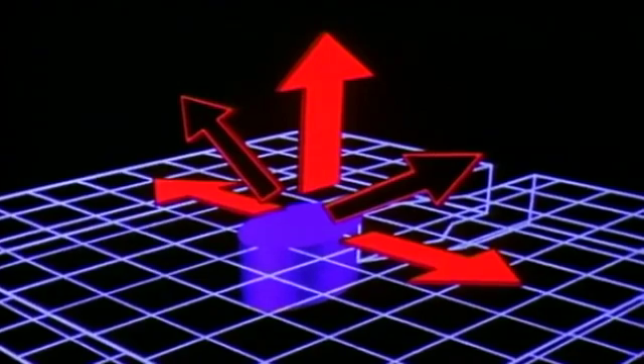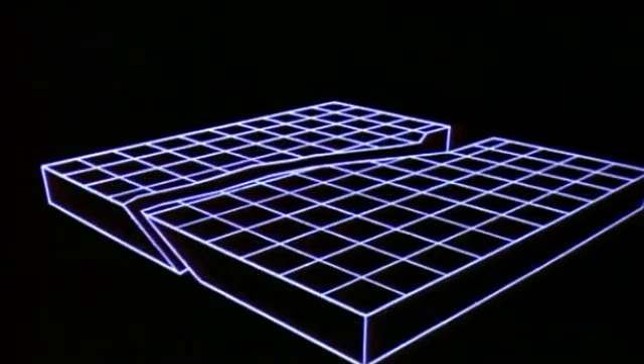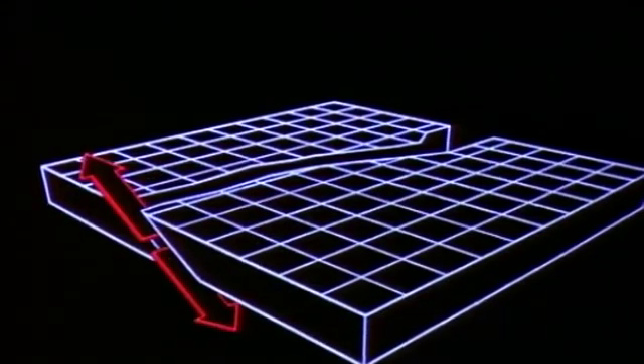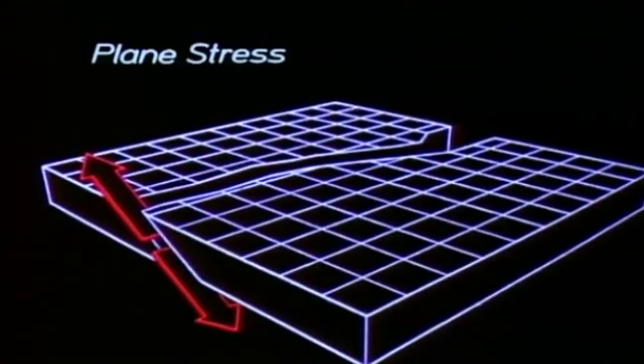How will this affect the fracture? Well, almost immediately the crack starts to move, it will move into material that has already suffered extensive shear at 45 degrees to the surface. The crack, being free of plane strain, turns through 45 degrees into one or other of the planes of maximum shear. In a very thin specimen, this is referred to as plane stress, and the fracture face will be at 45 degrees to the surface.